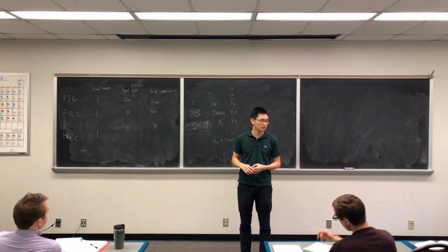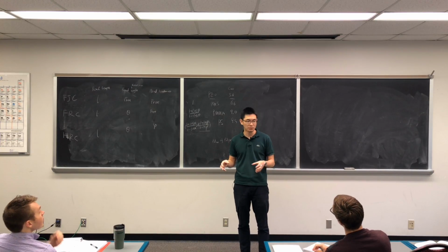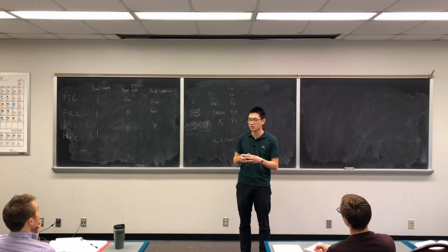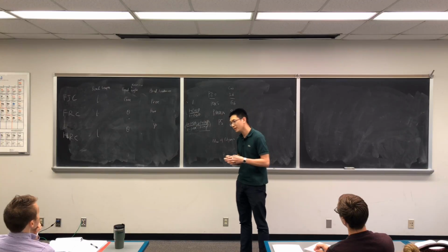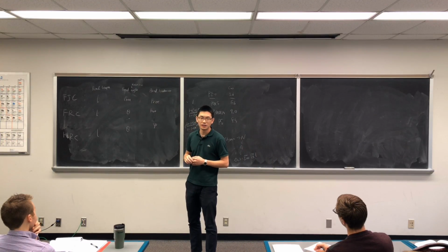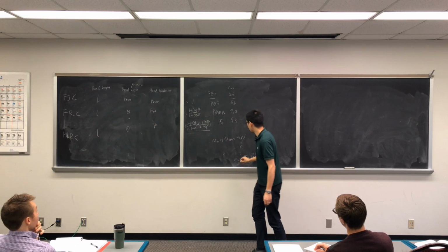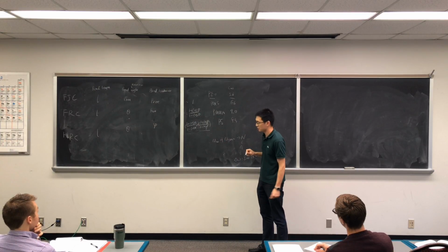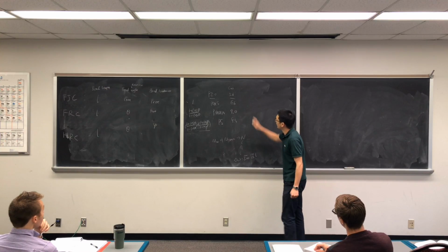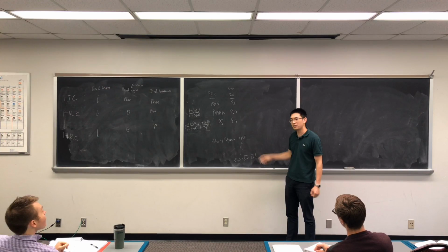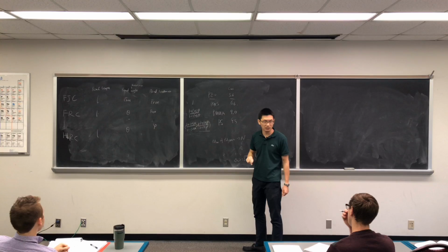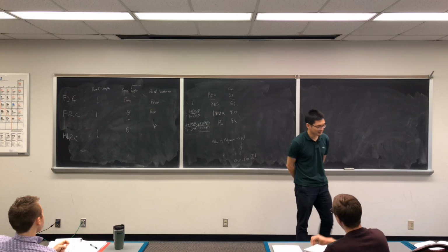Once you want to consider if one coil would be overlapped with another, you can estimate how big the coil is, and what the overlapping concentration would be if you assume these are packed as spheres over each other. These would be useful for this technique of looking at characteristic ratio. All right, so any questions for this part, how these characteristic ratio values are and how they can be potentially useful for you guys?